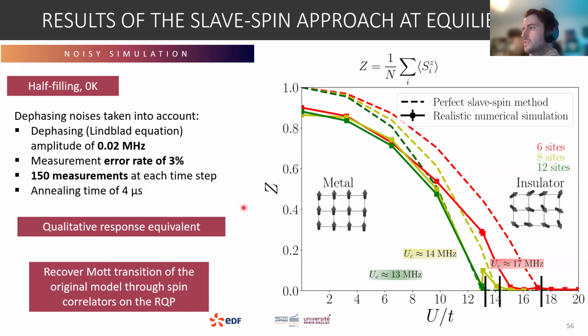And also the annealing time is limited, of course. We have a coherence time of our atoms, and we cannot perform annealing during a time which is too large. But despite all these sources of error and all this noise, we can recover here, in the full lines, qualitatively the same results as the perfect simulation. So here I have performed the simulation with some noise, and we see that we can recover, at least qualitatively, the phase transition.